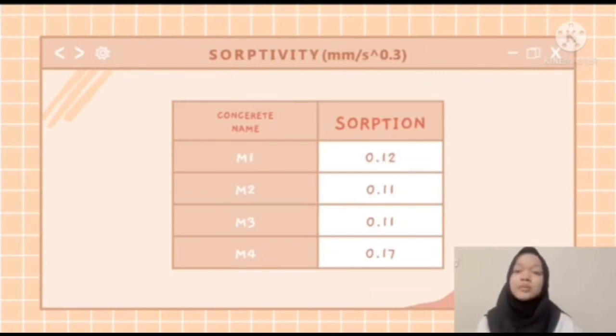sorptivity. From the table, we can conclude that sorptivity of the concrete was comparable with control concrete up to 10% eggshell powder replacement. However, sorptivity of 15% eggshell powder concrete was higher than control concrete. The maximum sorptivity was for eggshell powder replaced concrete with 0.17 mm per second to the power of 0.5. Sorptivity decreased with strength and increased with water absorption. That's all that we can conclude from the table of sorptivity tests.